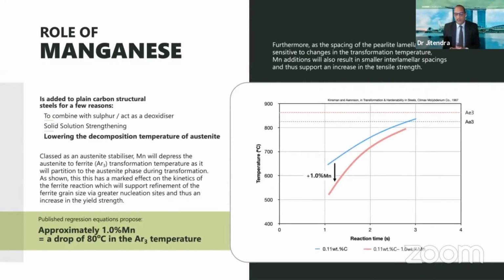But we do also know that the other additional contribution of manganese to strength is that manganese does depress the Ar3. This is the transformation point from austenite phase to ferrite phase. And it has been proposed that a 1% addition of manganese will drop the Ar3 by 80 degrees centigrade. So it acts very similar to water cooling when we leave the rolling mill, on the runout table: it depresses the transformation temperature and accelerates the transformation process once that Ar3 point is reached. So the addition of manganese acts through a similar mechanism to what water cooling would be doing.